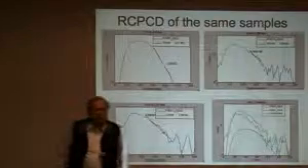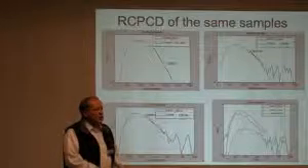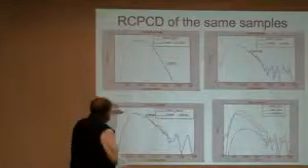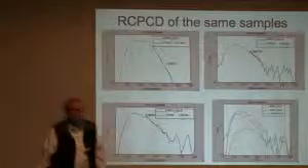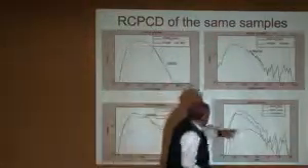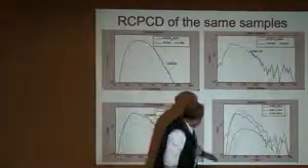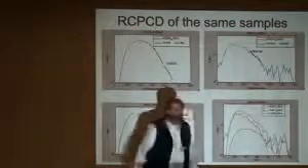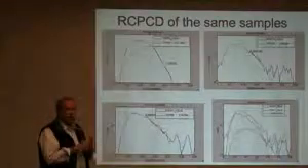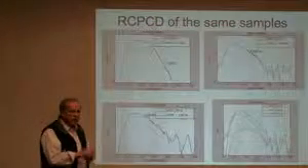Now, one of the other features that comes out of the photoconductive decay is that at constant energy flux, constant pulse intensity, the signal height is proportional to the carrier mobility. So I believe one of the things we do see here is a mobility variation, this being the most amorphous, this being the most crystalline, and we see that the signal intensity is increased by a good factor of 2 between those two. So I think that effect is quite real, that we see a higher mobility in the more crystalline sample than we see in the amorphous sample. That would be expected.